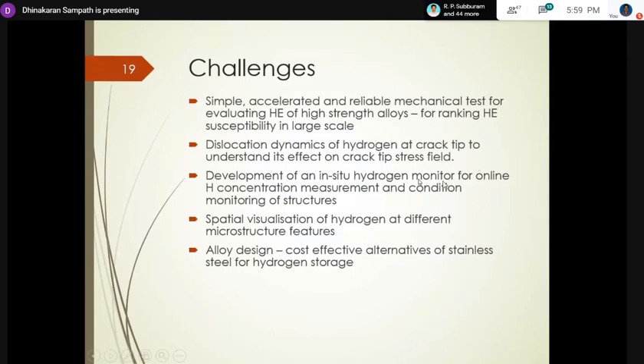Development of in situ hydrogen monitor. This is one key instrument which we can use to measure the hydrogen in the material or the surface, whether it is below the critical level, so that we can operate it. So one can use it as condition monitoring. Once it reaches some critical level, for example in steel, I'm not sure about this, but they just heat the material to a certain temperature, like 250 degrees centigrade, the hydrogen is all released, and then the material will behave like a normal material, unless there is some phase transformation. So that's one area to look at for condition monitoring.